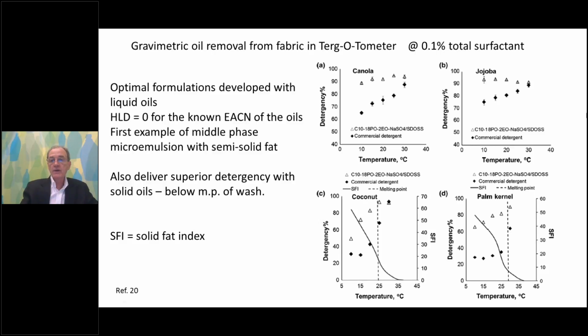What he did was, for a couple of liquid triglycerides, canola and jojoba oil, they used the HLD approach, measured the EACN of those oils, and then blended an extended surfactant with a twin-tailed surfactant to achieve optimum solubilization capacity for those oils, and then did detergency experiments. So we have detergency on the y-axis and temperature on the x, and determined the detergency as a function of temperature for these two liquid oils for these optimum formulations. We can see that the detergency remains very high for these liquid oils and significantly better than a commercial detergent that they used as a reference.